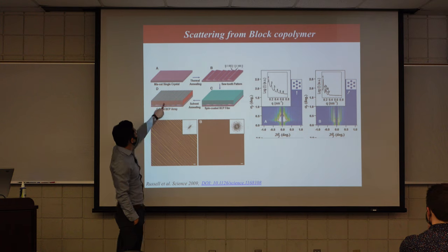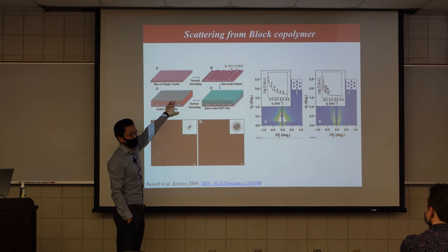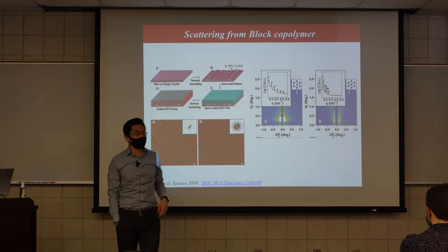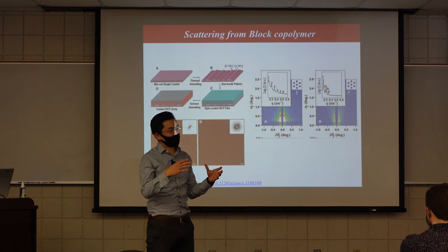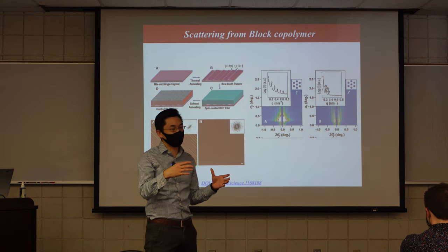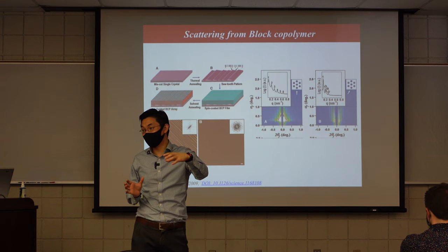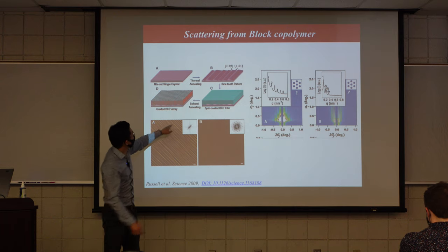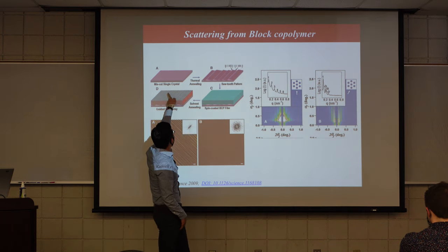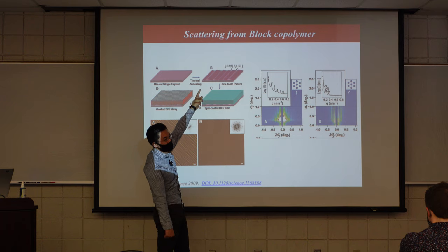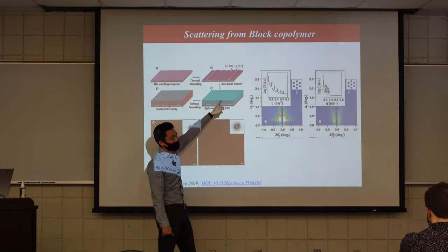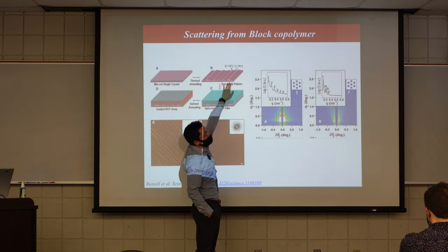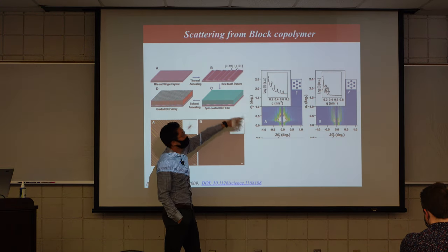The other problem is they typically have small grain boundary, and I'll show you later. Typically they have very good hexagonal order within a few microns. And outside the microns, like crystalline structure, they're going to form polycrystal. Your crystallites will adopt a different orientation. In this case, he actually showed you can use a biased substrate, which is a miscut crystal from sapphire, which is an inorganic ceramic, then you can heat up at high temperature. It will form these crystalline facets, okay?